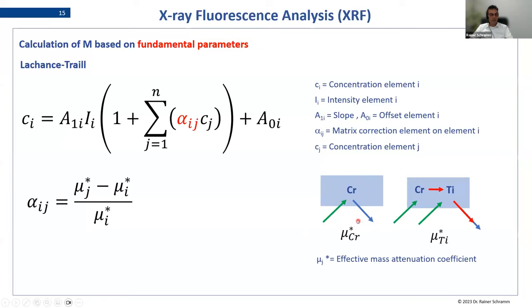and this is first observed for the element of interest. And then, of course, we have to do this for all the elements which disturb our chromium intensity, either by exciting it more or absorbing it. And having both together, we could calculate our alpha coefficient. And in this way, we can do the matrix correction for all disturbing elements in these samples.